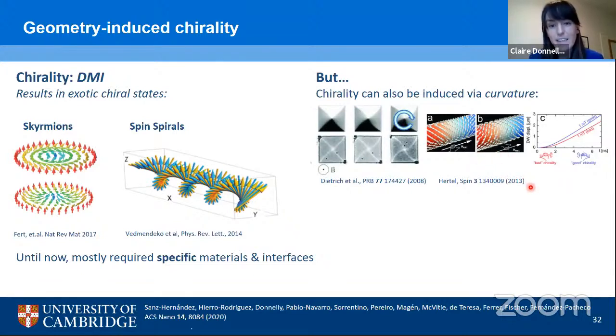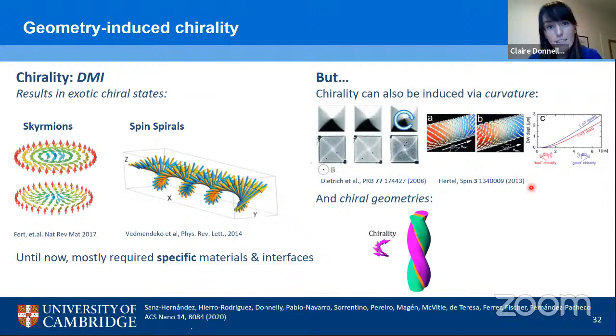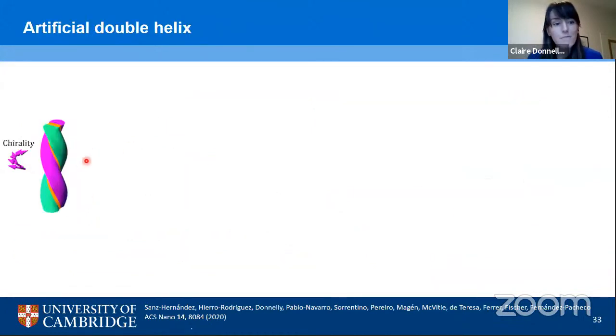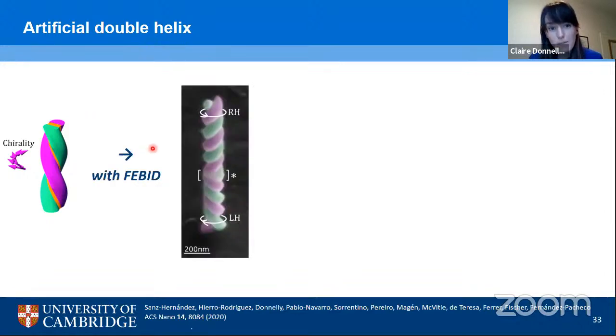Now, what we are interested in here is going to chirality in a more direct fashion, via the 3D printing of chiral geometries on the nanoscale. And specifically, when we're talking about chiral geometries, we're talking about perhaps one of the most well-known chiral geometries, and that is a helix. In this case, we're looking at a double helix. We pattern these structures with FEBID, and you can see here in this SEM image, the colors are artificial, they're just to guide the eye to show that we really have these intertwined double